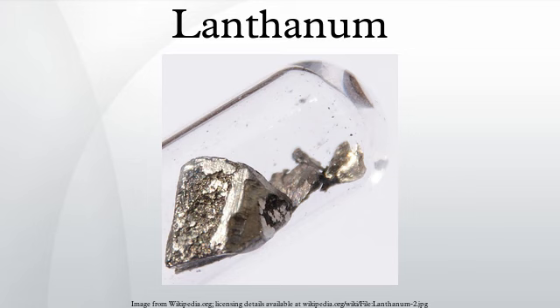The rare earth ions are then selectively washed out by a suitable complexing agent, such as ammonium citrate or nitrilotriacetate. Lanthanum can also be separated from a solution of rare earth nitrates by liquid-liquid extraction with a suitable organic liquid, such as tributyl phosphate. Currently, the most widely used extractant for the purification of lanthanum and the other lanthanides is the 2-ethylhexyl ester of 2-ethylhexylphosphonic acid. This has better handling characteristics than the previously used bis-2-ethylhexyl phosphate.